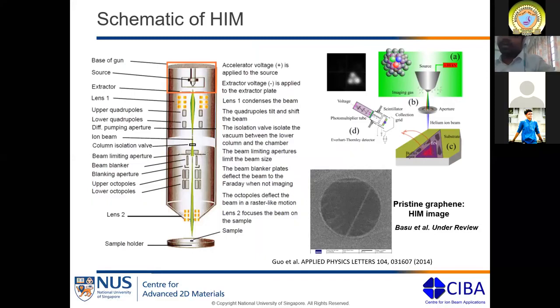The beauty of this instrument is that you can create a source size of a single atom. For example, if you look at this picture, you can only see three ball-like structures, and these are nothing but three atoms at the tip of the source. The source is made out of tungsten wire, which is very sharp, and on top you have only three atoms. Out of these three atoms, you can select only one atom, and then you use that atom as a virtual source to generate the ion beams.